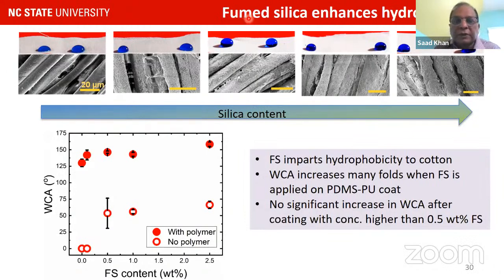We have done a lot of work in our lab on fumed silica, so we thought, why not use fumed silica? Fumed silica is branched silica, and it can have hydrophobic or hydrophilic functional groups. The one we use is hydrophobic. You can see here the water droplets on the fabric. This is pure fabric. As we add more silica, the water droplet becomes more round, suggesting that this is non-wetting. If you look at the water contact angle, when we add fumed silica to the polymer, there is some jump, and then it stays stable. So the fumed silica does impart hydrophobicity to cotton.